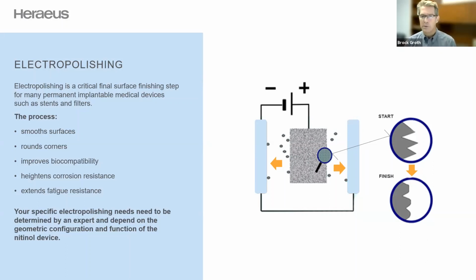One of the other benefits that electropolishing will give you is improved biocompatibility. This will happen through several mechanisms. This removal of material will give you this nice surface finish that will create less trauma to the tissue that it's coming in contact with, but electropolishing will also lay down a thin adherent oxide layer, and this will improve your corrosion resistance. The main method for testing corrosion resistance in small implantable medical devices or nickel titanium implantable devices is potentiodynamic corrosion testing, ASTM F2129, and it measures the breakthrough potential. This thin adherent oxide layer will prevent that breakthrough of corrosion and will give you better corrosion resistance.